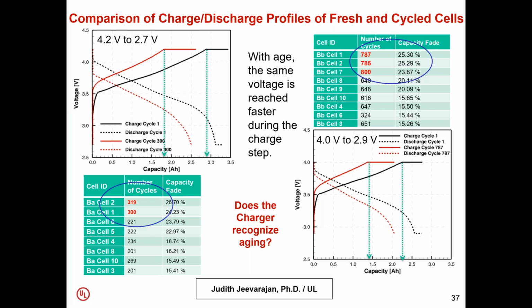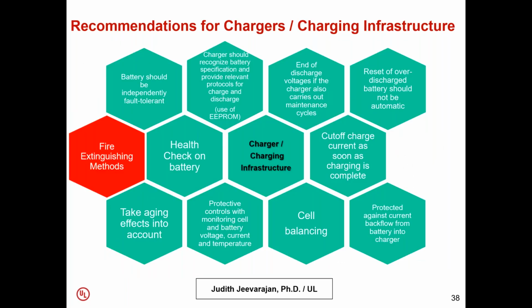Another thing that I wanted to point out that is significant is using the battery in a voltage range that is shorter than what the manufacturer specifies. When we reduced our voltage range of operation to between 4 volts and 2.9 volts, which is a 200 millivolt reduction on either end, what we found is that we more than double the number of cycles that we get from the battery.